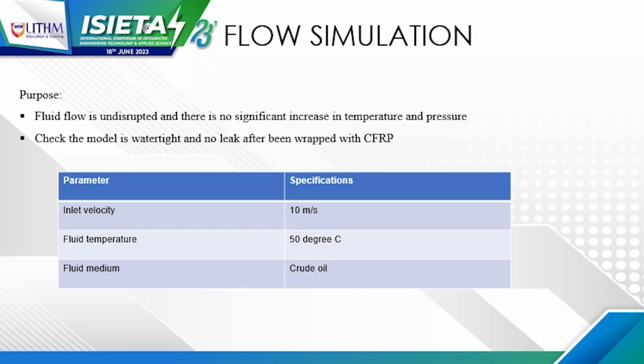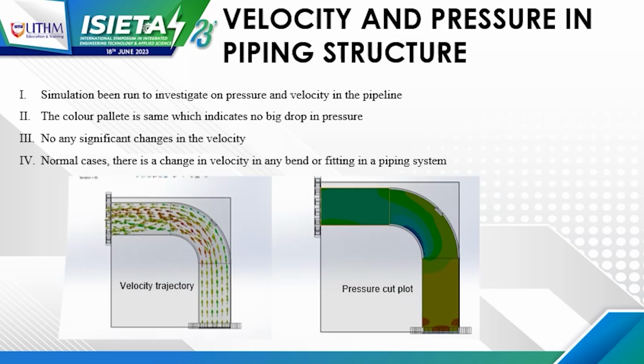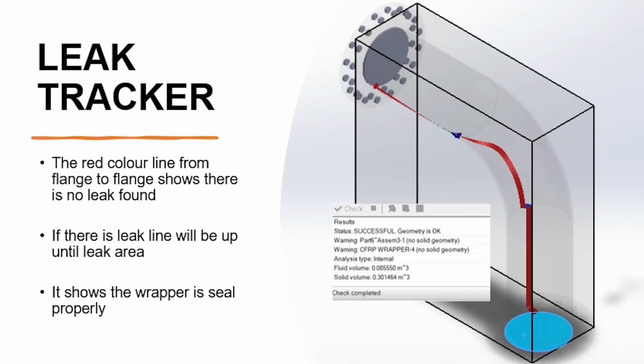For flow simulation, these are the parameters: 10 meters per second, 50 degrees Celsius, and crude oil. This is to see whether the flow is disrupted or not. This is the velocity trajectory and pressure cut plot. There was no big drop in pressure or significant change in velocity. Only in normal cases is there a change in velocity at any bend or fitting in the piping system. This is the leak tracker. It shows there's no leak, as the red line connects from one flange to another flange and the geometry is okay. So it shows the wrap is sealed properly.